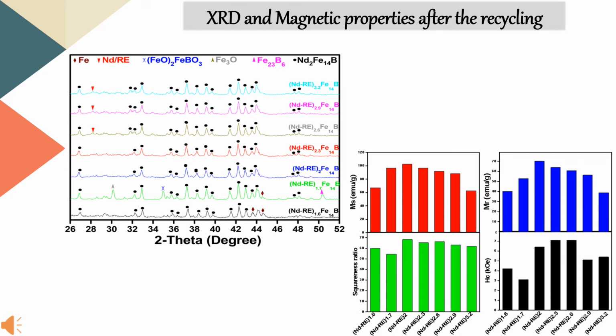We got 7 different compositions. NdRe1.6Fe14B is the original composition of the magnetic particles recycled from the sludge, but because of the addition of rare earth, different compositions were obtained. Iron and boron are always constant; we didn't add any iron. Iron is 14, but because of adding extra Nd, the NdRe quantity changed, like 1.7, NdRe2, NdRe2.3, NdRe2.6, NdRe2.9 or NdRe3.2, but iron is always 14 and boron is always 1, so that ratio is constant.